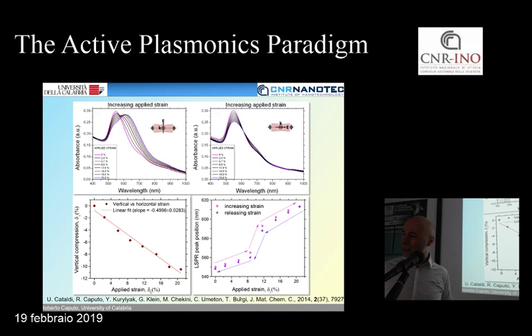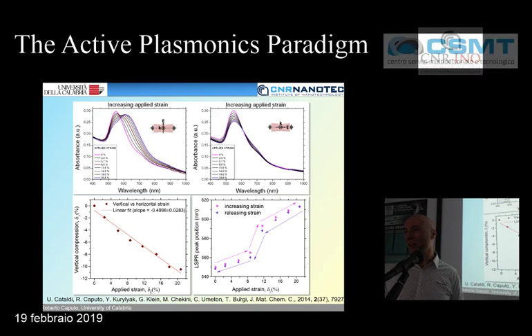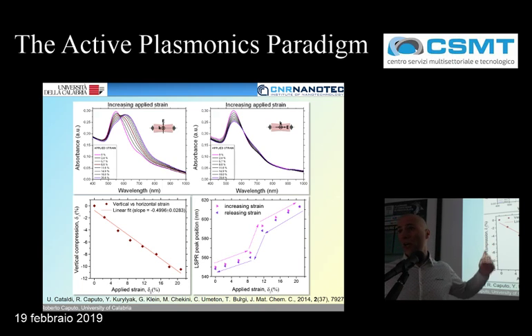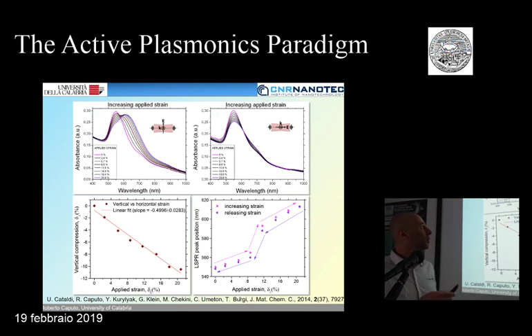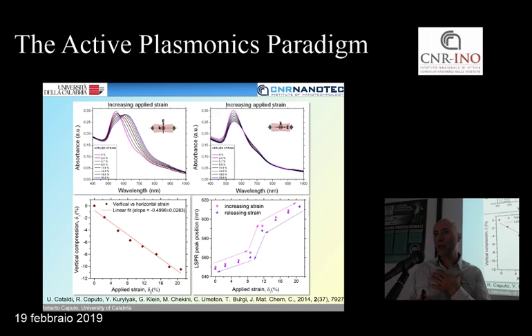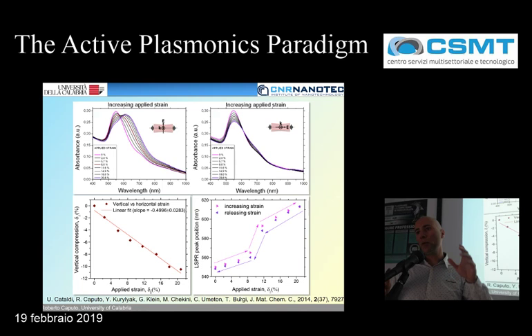It's a very nice question because you are going to a very deep insight into the situation. For answering your first question, indeed, when you consider this family of curves, you have, in principle, one peak which is decreasing and another peak which is increasing. So I explain this situation to myself in the way that, in practice, you have all the particles of your sample working together to give these peaks.